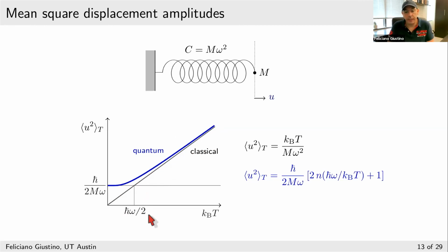For example, if you are considering a perovskite with lead, typical phonon energies are of the order of maybe 10 millielectronvolts. That means that this value here will be approximately 5 millielectronvolts, and that's 1/5 of room temperature. So we are saying that this is approximately 60 Kelvin in perovskites. So room temperature will be approximately here. So maybe your system can be described using classical molecular dynamics.